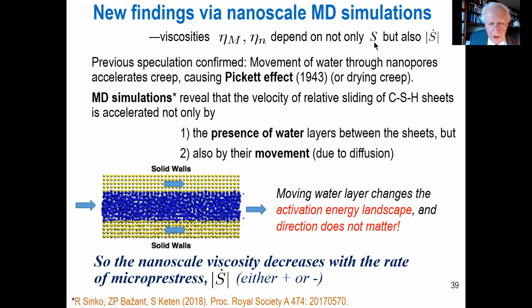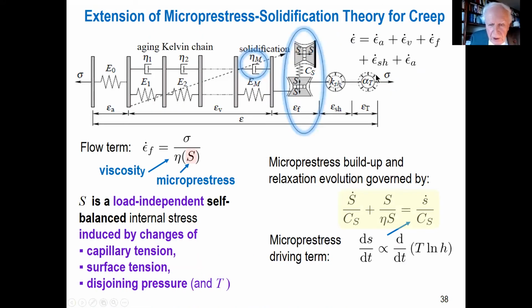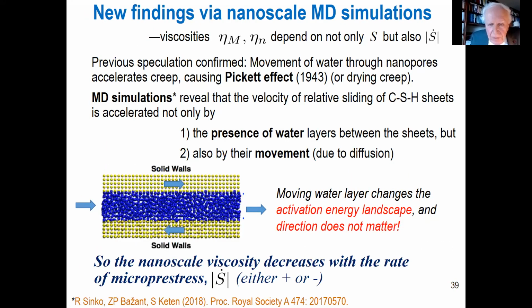Now, it was found by Jirasek and Havlasek that predictions in some cases were not good. And in fact, it gave, for drying creep of very different specimen sizes, a reverse size effect. So size effect is always indicative, important to watch. And we found that a way to fit it was to add a term which was shown here. Now it is shown in the next slide, that there is a dependence on S dot. Now, how to explain it?